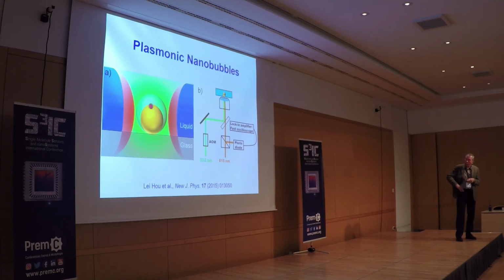Right, so now there will be this change of temperature, and when the temperature is changed, the index of refraction will also change, and a second beam at a different frequency, for example 800 nanometer, will be scattered in a slightly different way. So our signal here will be changed by the temperature change. So this is a way in which you can also measure the temperature in a much more intricate, indirect way than the anti-Stokes photoluminescence I discussed before.